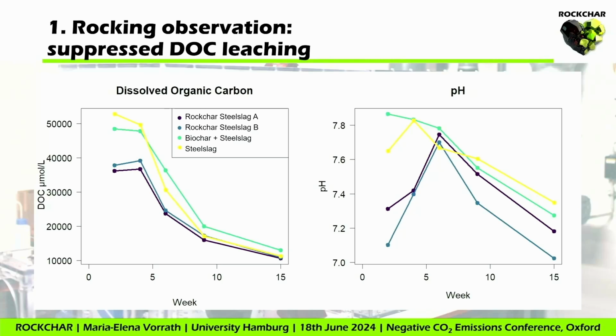DOC. So what I have now observed is the steel slag is causing a very high pH shift. The ROCKCHAR with steel slag is not changing the pH of my soil so much. Compared to the other one, so the pure steel slag and the steel slag with biochar, the co-deployment, it's quite low. And I can see the immediate effect on the DOC leaching, that less organic carbon is lost from the soil. So obviously, the CDR potential of my ROCKCHAR based on steel slag is better than the simple co-deployment or the single deployment of steel slag.